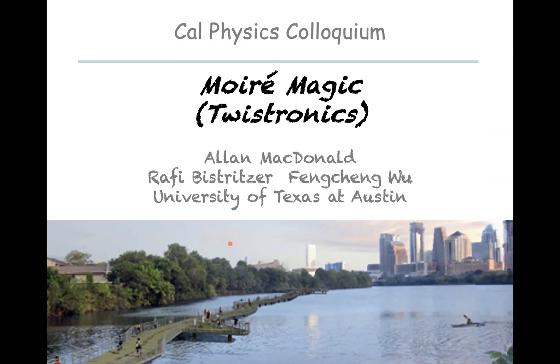Are these s-wave superconductors? I don't think that is known. I think the common picture is that the pairing occurs in a ferromagnetic state, so they're spin triplet, but there's also this valley degree of freedom, and in that case they would be valley singlets. And because valley acts so much like just a pseudospin label, except for the electron-phonon scattering, of course, it behaves very much like a spin singlet superconductor.